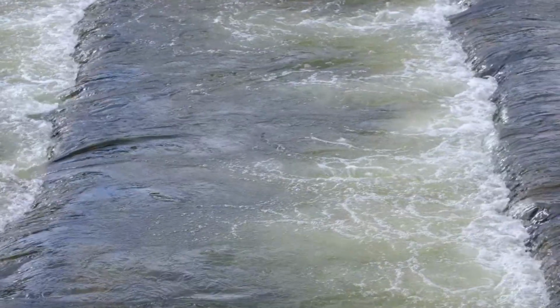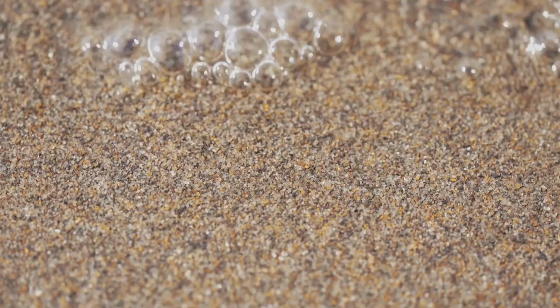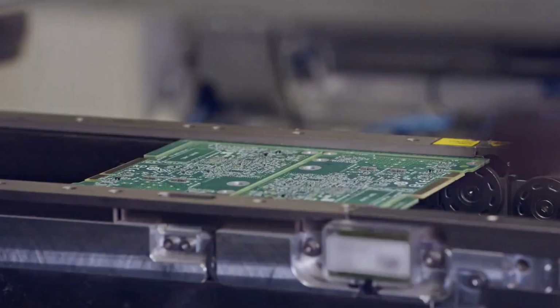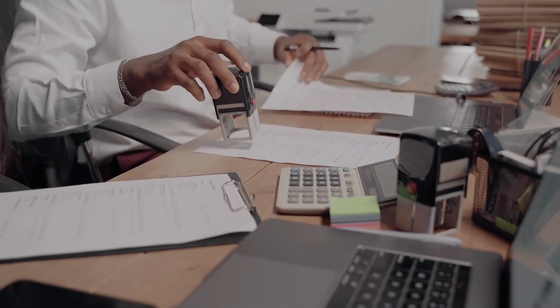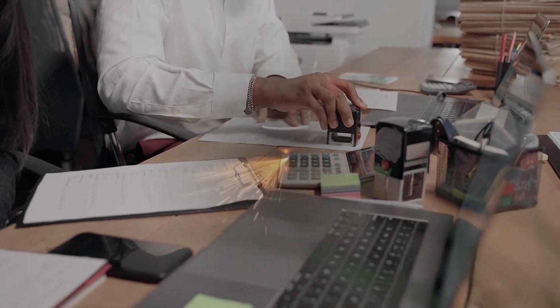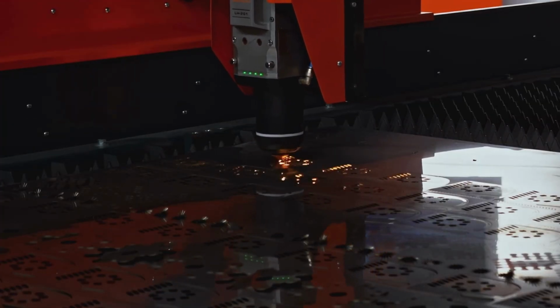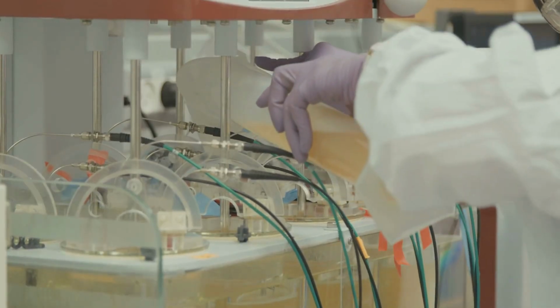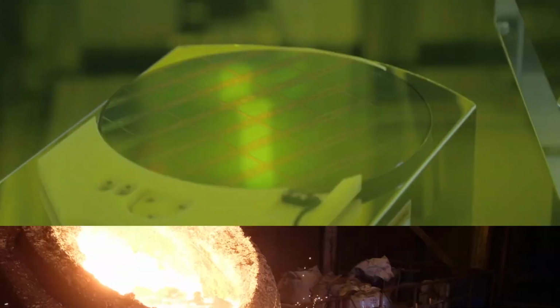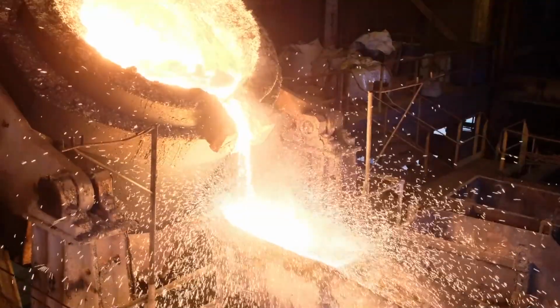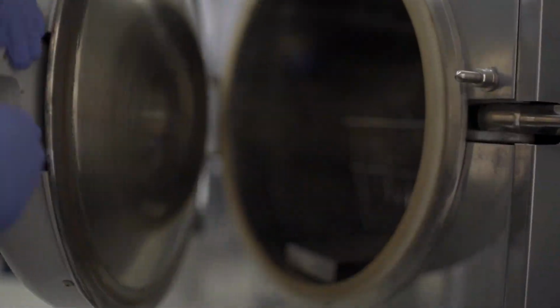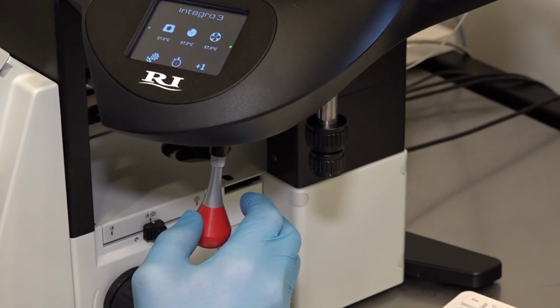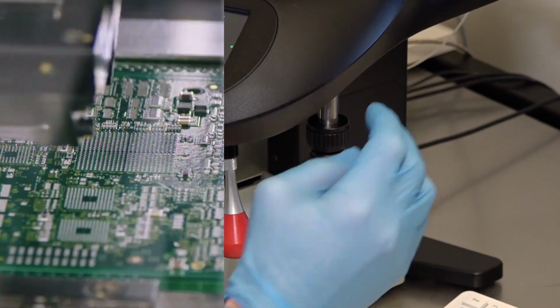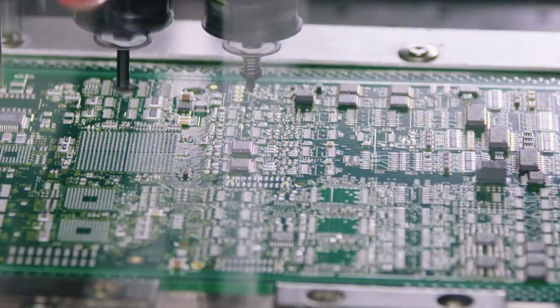Refining copper to 6N is like filtering a swimming pool until it contains fewer than 1 grain of sand per 10 Olympic pools of water, and then doing that reliably at industrial volume with a traceable certificate for every batch. That is the gap. Japan's Mitsubishi Materials and JX Metals and Western specialists like Materion in the United States have historically led in ultra-high purity semiconductor-grade target manufacturing. China has a domestic target maker in Griken Advanced Materials, which produces physical vapor deposition targets and whose product lines and customer references are corroborated. But whether Griken's highest purity products meet leading-edge specification at confirmed production volume, that has not been independently verified.